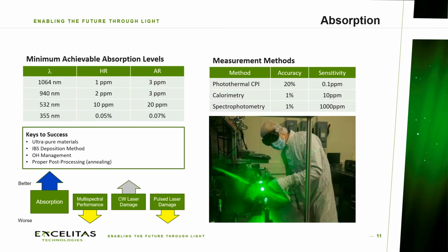We will typically get good CW laser damage coming along with that. The pulse laser damage may actually decrease a little bit because the material choices are usually not the same. And we could be challenged with some multispectral requirements because of the complexity of the films that would be required for those applications. So the spectral requirements are sometimes the thing that can require the most optimization and refinement to get the optimal trade space for a given application, particularly when we're talking about managing multiple bands.